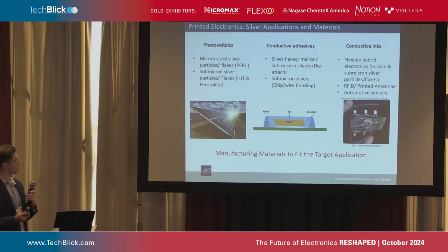So some printed electronics applications where we fit in. PV, specifically PERC, we're typically sending micron-sized silver particles and flakes, usually on the larger side, higher temp. Then on the lower temp side, we have your heterojunction and perovskite. And these typically we will sell our submicron silver particles and flakes, less than 1 micron. On the conductive adhesive side, you have your die attach and your chip wire bonding. So this can be on your fired or your sintered materials. So this can be micron or submicron sized flakes, nano silvers as well as submicron silvers.